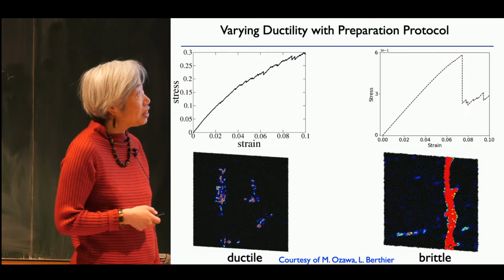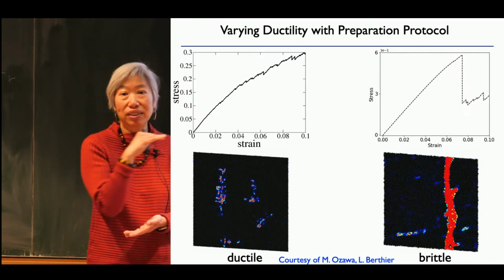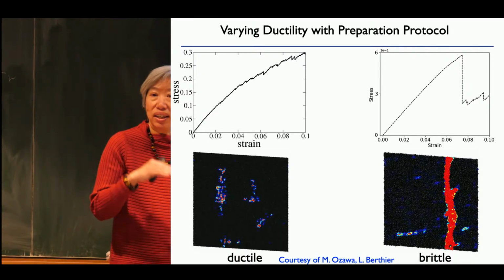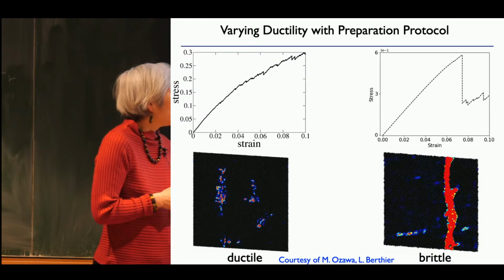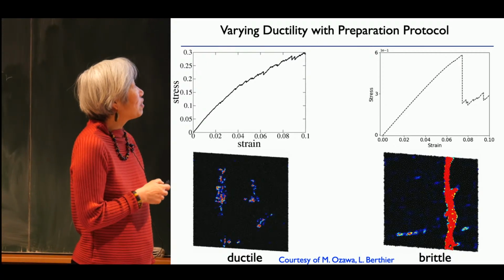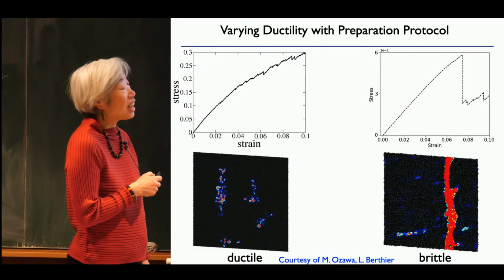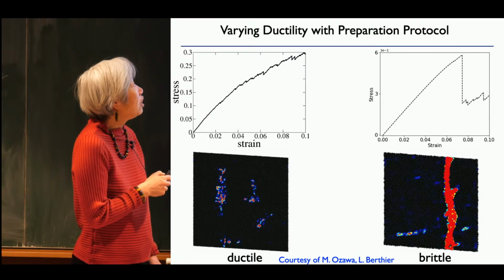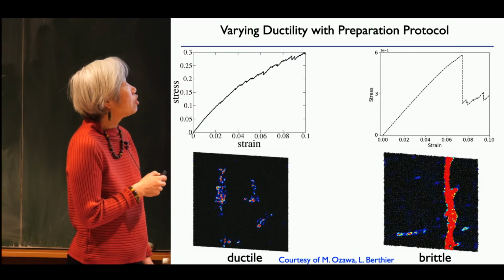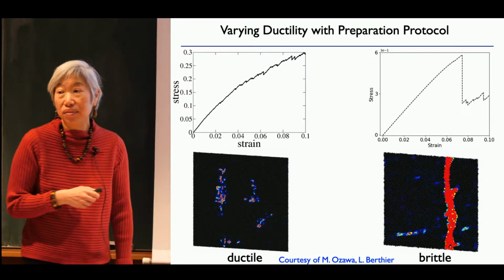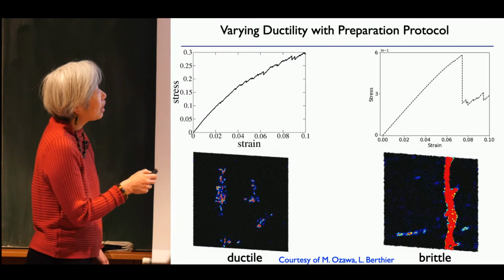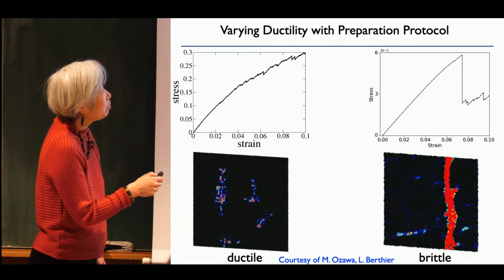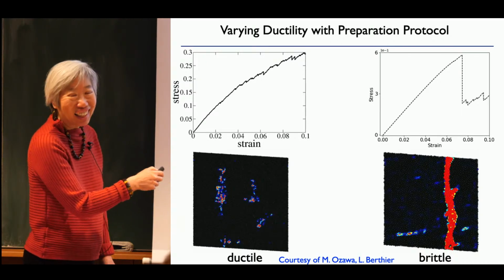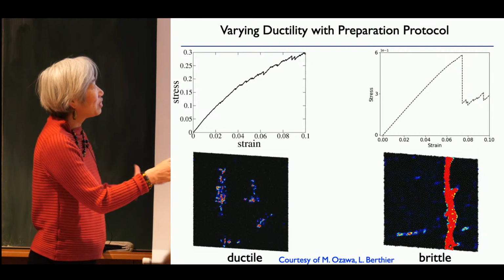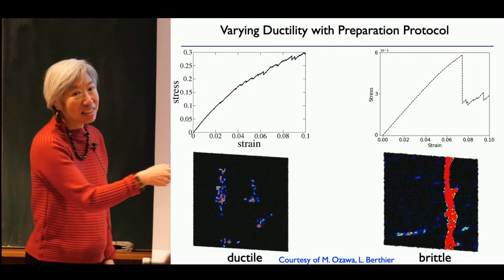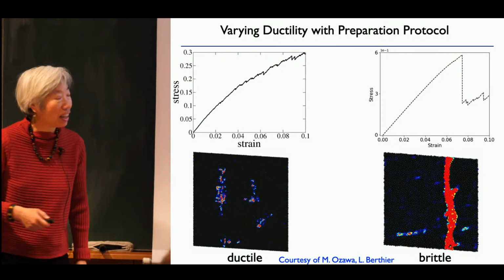And when you take these two systems, and now you shear it very slowly at 0 temperature, what you see is a stress-strain curve that looks like this. So it's initially elastic, but then you start seeing these little stress drops. As the system goes, it eventually flattens out. And I keep pushing, I still don't, for some reason, have this plot of this flattening out eventually.